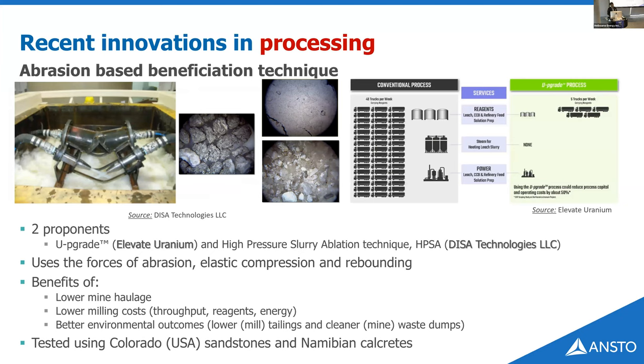Now, I mentioned earlier that radiometric sorting worked well. Yes, it does. But the other technique that has come across and is being considered by two proponents now is this abrasion-based technique. So Elevate Uranium, which is an Australian mob, is looking at it for their Marenica operations in Namibia. And a high pressure slurry ablation technique has been developed by DISA Technologies. They're both looking at taking the uranium-containing particles, rubbing them across each other and removing the fines. And the uranium typically is actually in the fines.